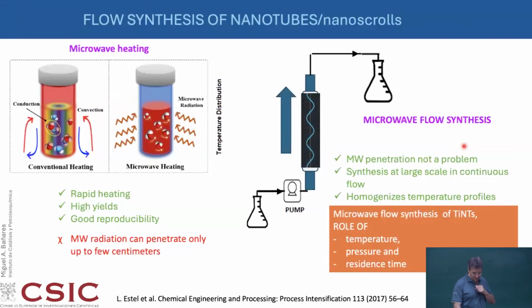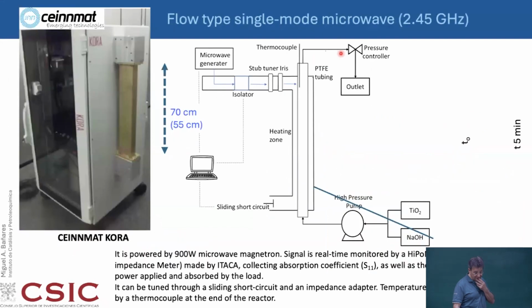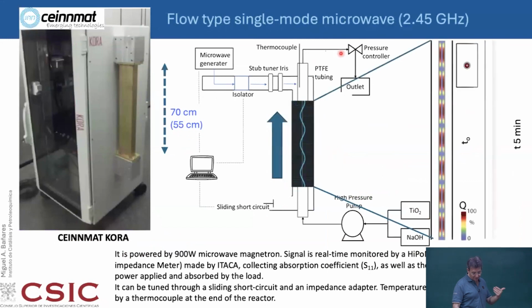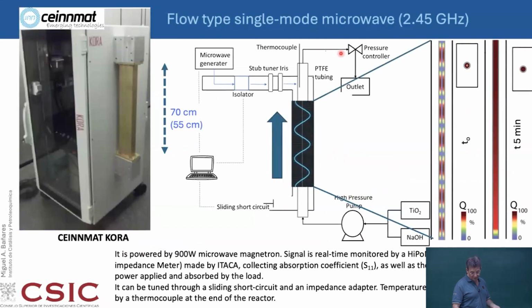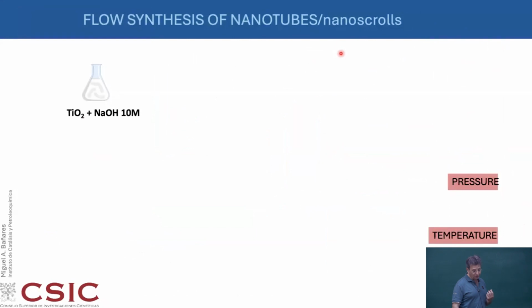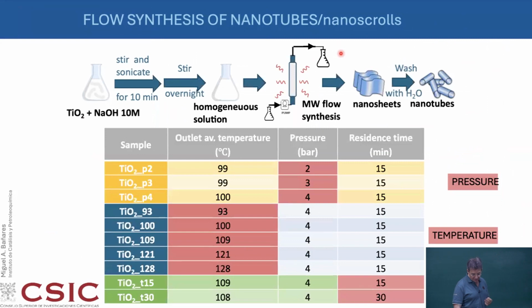And basically, this is the standing wave, and then we flow into it this solution of sodium hydroxide and titanium. And what you get at the end of the process up there is the sodium titanate. Now, the way this sodium titanate is made is controlled by the temperature and by the pressure and by the flow. So you can control it much better than in a hydrothermal synthesis, which is in a closed system, because you have a continuous feed and a continuous output. And so here you can play 1, 2, 3, 4 bars. This is a water solution, but we have a pressure valve in the system.